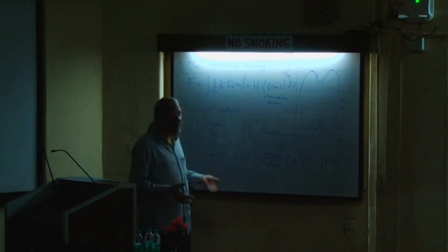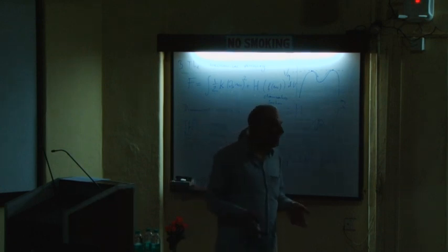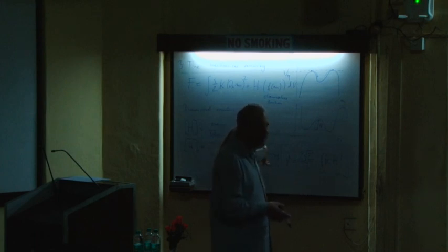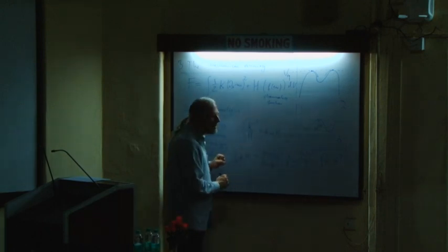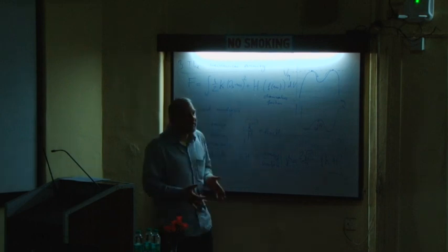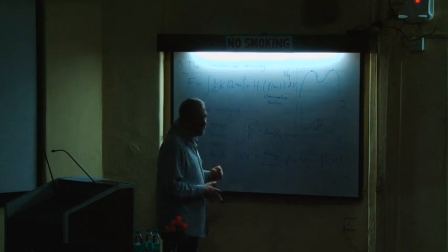And from this dimensional analysis, you can obtain that if you change the double well function from the fourth order polynomial to some other function, well, maybe the prefactors will change. There will be no exact 2 square root of 2 by 3. It might be 0.7892. You might be forced to calculate this numerically. But the general scaling behavior will always be like that. That is, these two coefficients or these two terms in the functional fix the interface free energy, and they fix the interface width.